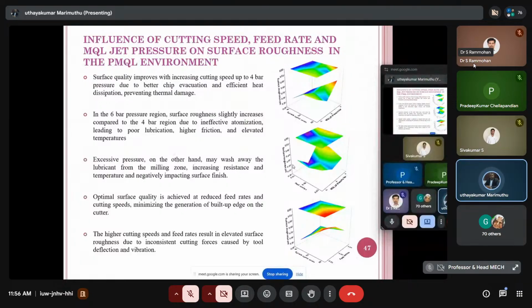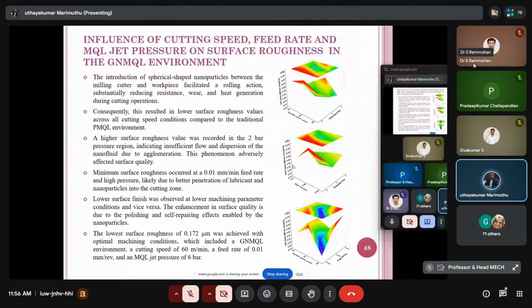Optimal surface quality is achieved at reduced feed rates and cutting speeds, minimizing the generation of built-up edge on the cutter. The higher cutting speeds and feed rates result in elevated surface roughness due to inconsistent cutting forces caused by tool deflection. Actually, cutting force also we can take, but we didn't take this one. By means of an instrument, a cutting force dynamometer, we can measure that. So this is about the surface roughness in the GNMQL environment.